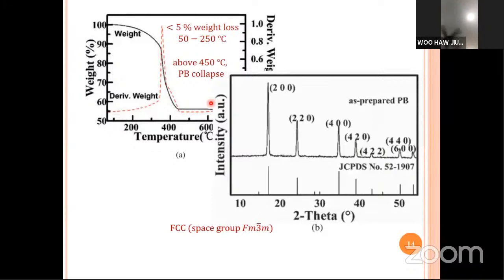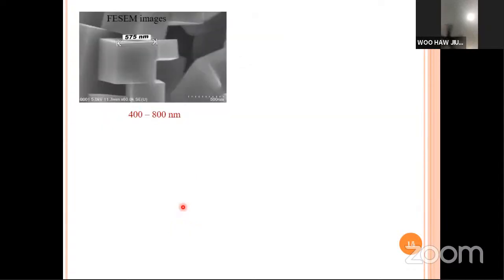Then we also sent it for XRD. This is the XRD spectra. Basically, all the peaks are sharp and strong, and they're in agreement with the library data from JCPDS number 52-1907, with all the important peaks agreeing, okay? And it has the space group Fm-3m, a cubic structure. Then we also look at the FESEM images. Basically, we have a distribution of different sizes of cubes between 400 to 800 nanometers.